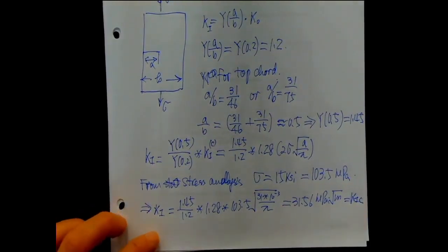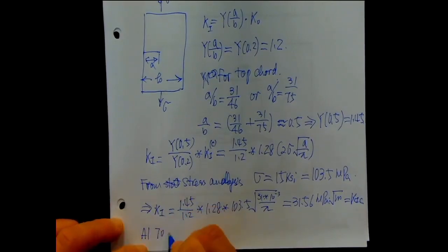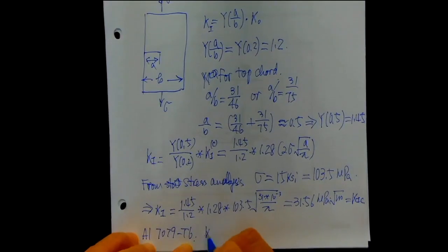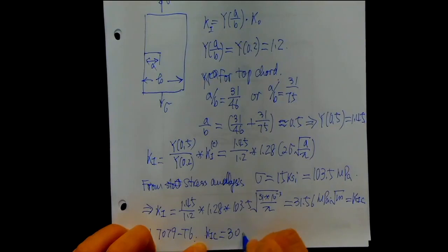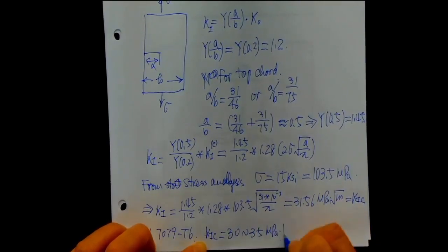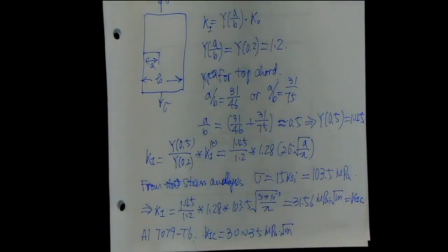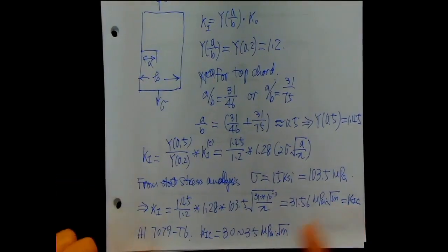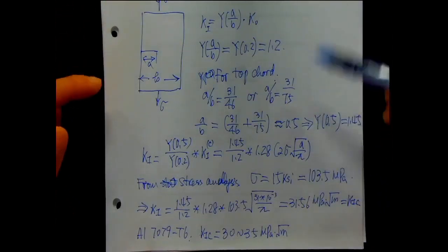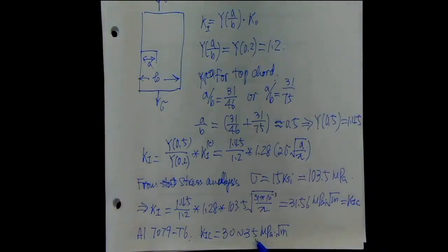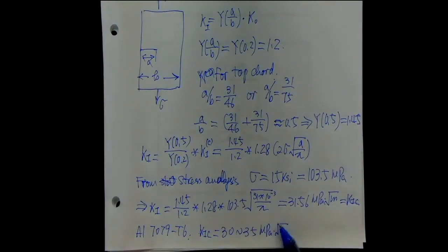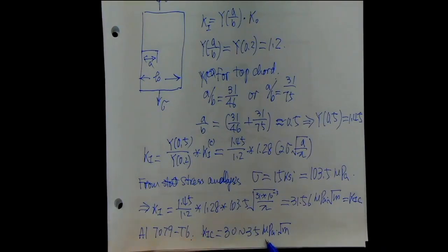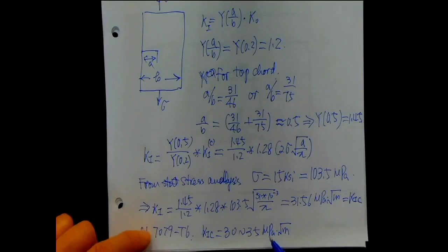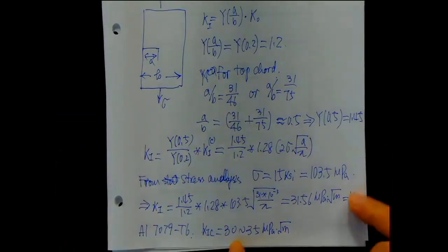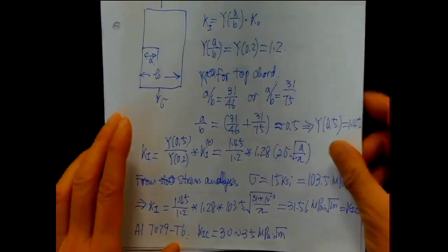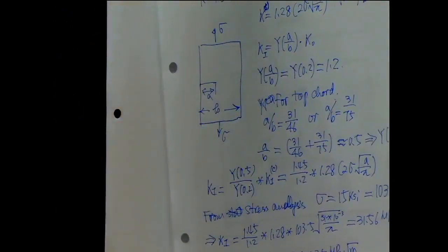And for the aluminum material, they have a 7079 T6, and based on the material data sheet, the K1C is between 30 to 35 megapascal root meter. So this definitely is within that range. That gives them confidence that even though they have done some approximations, it gets very close within the range. In case you find that this number is much lower, either you have to go back to look at your calculation, or you have to find out whether the material has some problem, right? Because this is within that range, you can see the crack behaved like what it's supposed to.